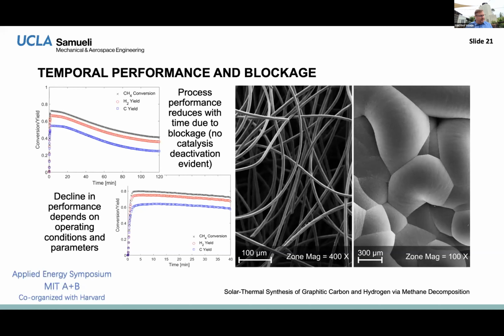In fact, people who worked on methane pyrolysis spent their whole careers doing it. When they see this, I talk to them, they say, well, how can you do this without a catalyst? Maybe they could see you could get carbon black or some very low grade carbon, but the fact that we're getting this beautifully ordered graphitic product is a big surprise to people in the field. And it's been done before to some extent, but only with a catalyst.